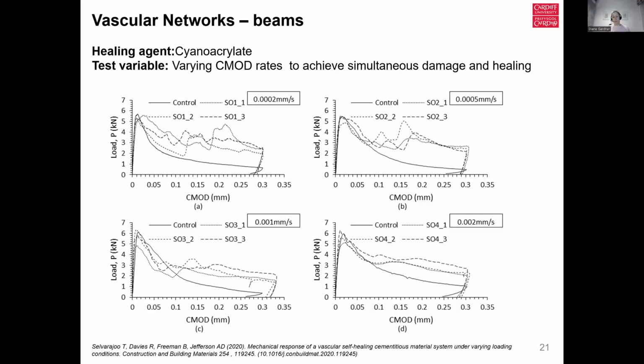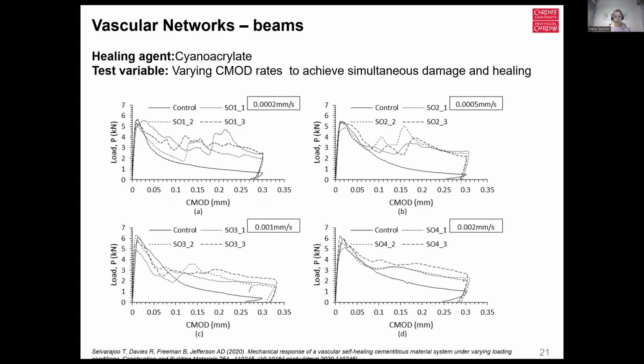So as a bit of crack was healed, it would reach a higher strength, it would then crack again. The graphs on the slide show considerable variability both within the test sets and between sets, and it's noticeable that the responses become smoother as the CMOD rate increases. The latter trend is attributed to the fact that as the CMOD rate increases, so does the rate at which the healed material is also re-stressed. And therefore, each elemental area of healed material reaches the re-damage threshold more quickly and in any one location. The relative area of healed material that has reached this threshold is less, and this results in smaller jumps in the response due to rehealing and damage.